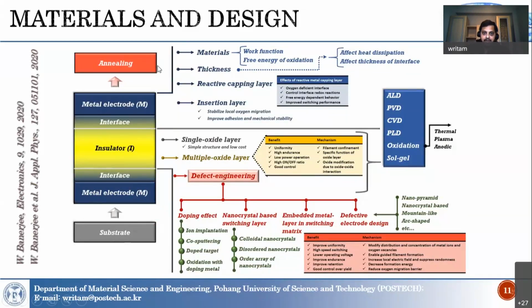Going step by step, from the very top side you can change the material thickness, different capping layers with different kinds of interface layers. And in the oxide, you can have several kinds of oxide layers, single layers, multiple layers, and you can use different systems like ALD, PVD, CVD, PLD, and so on.